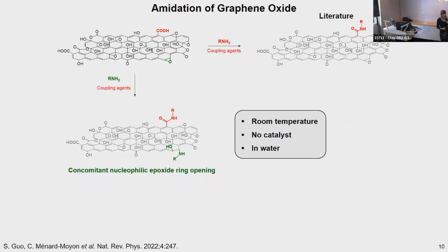As I mentioned before, epoxides are present in a large amount, and they are highly reactive towards amines. So in fact, in these conditions, there are two reactions occurring, the epoxide ring opening and the amidation reaction. The epoxide ring opening is a reaction which is very fast, actually. It can occur at room temperature, in water, so in very mild conditions, and there is no need of catalyst.